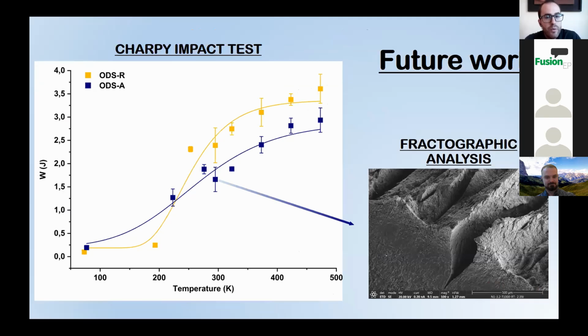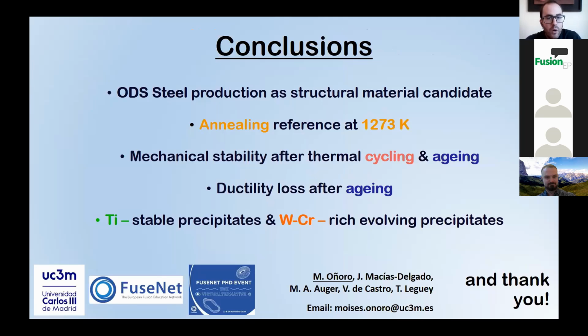Finally, we are currently focused on Charpy impact tests and surface fractographic analysis. We obtained the first results for the annealed and aged samples that will lead us to report the ductile to brittle transition temperatures and the involved fracture mechanisms. To conclude, I point out the most important results of our research so far, based on the characterization of an ODS ferritic steel and its thermal stability after annealing, cycling, and long-term aging thermal treatments.